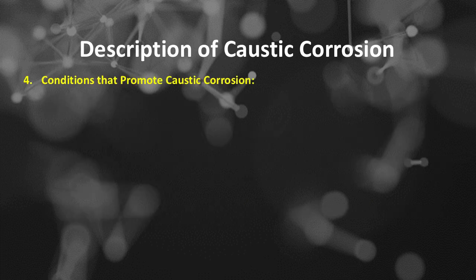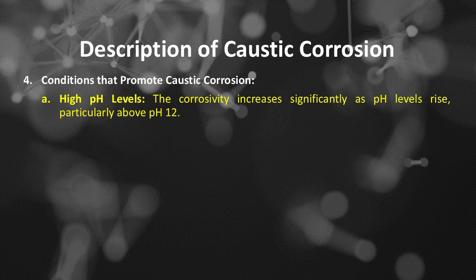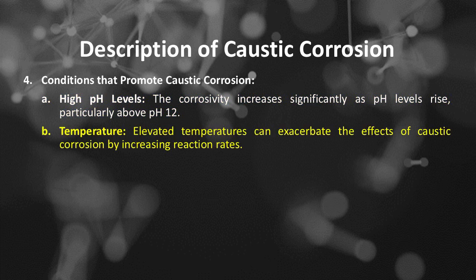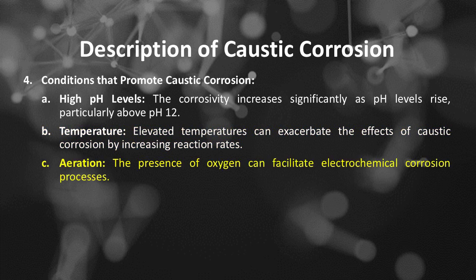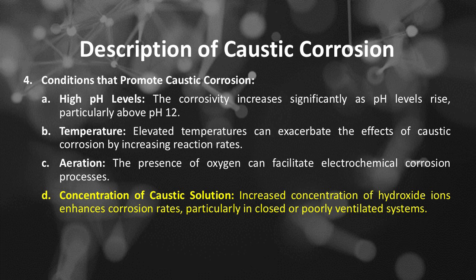Number 4 is conditions that promote caustic corrosion. High pH levels: the corrosivity increases significantly as pH levels rise, particularly above pH 12. Temperature: elevated temperatures can exacerbate the effects of caustic corrosion by increasing reaction rates. Aeration: the presence of oxygen can facilitate electrochemical corrosion processes. Concentration of caustic solution: increased concentration of hydroxide ions enhances corrosion rates, particularly in closed or poorly ventilated systems.